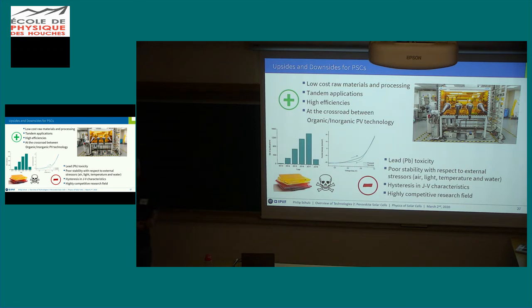There was an attempt to introduce a hysteresis index, that is the area under this curve for each cell, in order to quantify hysteresis. This has failed spectacularly because this kind of behavior really depends on your scan speed. If you scan very slowly, you may not see hysteresis at all, because processes such as ion migration and build-up of an interphase layer at the interfaces can happen on a minute scale or the scale of seconds. It really depends on the interfaces that you design for the perovskite cell.